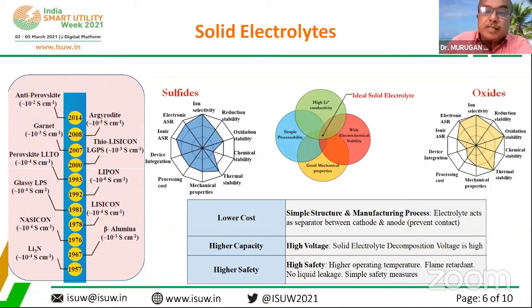So among sulfides and oxides, the ideal solid electrolyte should have all these four characteristics. High lithium ion conductivity at ambient conditions and wide electrochemical stability. If someone is able to find an electrode which can produce 7 volt or 8 volt, that potential window should be capable. And good mechanical properties, and from the technological point of view, a simple process. By keeping these four, the lower cost comes down, the price we can bring down because of the simple structure and manufacturing process.